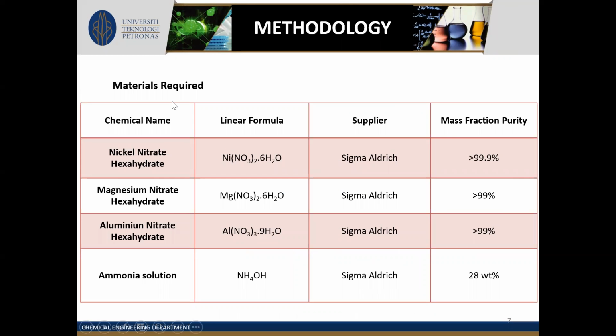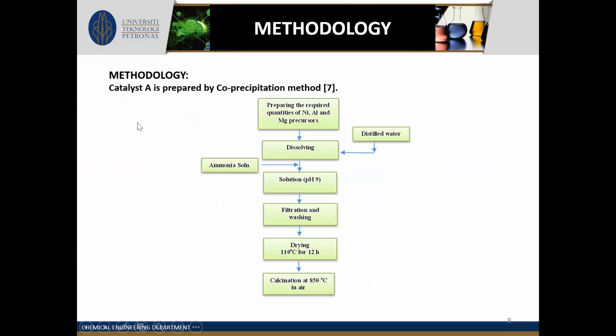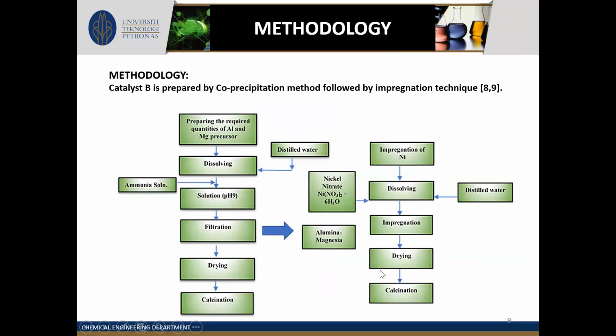These are the main materials which have been used to synthesize the catalyst: the hexahydrate salts of nickel, magnesium, and aluminum, and ammonia solution as a precipitating agent. For methodology one, to prepare catalyst A, we used a single-step technique in which we mixed the stoichiometric amounts of salts of nickel, aluminum, and magnesium, dissolving them in water, and then added ammonia solution dropwise for precipitation, maintaining a pH of 9 throughout the reaction of 12 hours. Then we filtered and washed our precipitate. We then put it in the oven for drying for 12 hours at 110 degrees Celsius. Finally, calcination of the catalyst is done for 5 hours at 850 degrees Celsius.